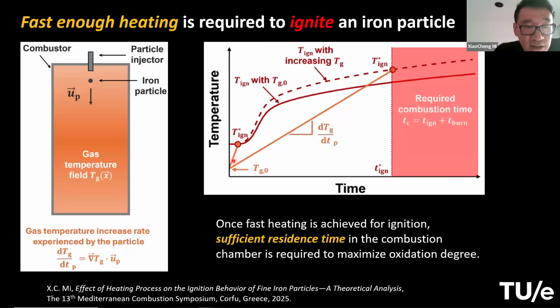And if you can heat the particle very rapidly, it will cross the ignition temperature curve at a lower value. That means if you can heat the particle faster, it's more likely you can ignite it. But if the particle experiences a much slower heating rate, it requires a much higher temperature to be ignited, and also takes a longer time to reach that ignition temperature. Right? So the conclusion is that fast heating is required to achieve ignition. And after that, you also need a sufficient residence time in the combustion chamber to make sure the particle can complete its oxidation, which is the topic I'm going to talk about a bit later.